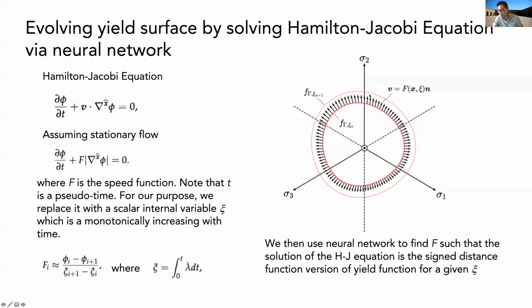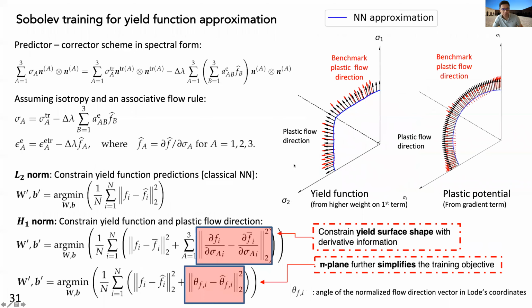So once we have the new solutions, we solve the reinitialization problem, then we generate a set of solutions of those Hamilton-Jacobi equations, and the rest is just to use the level set to train it. The training is pretty much the same, except that the network is trained for the same given internal variable. So there are multiple yield surfaces, the initial yield surface and then the yield surface at a different given internal variable. And then what we're trying to do is train it with a super simple supervised machine learning, and then we can generate the evolution, not just a single yield surface, but how the yield surface evolves over the change of the internal variable.